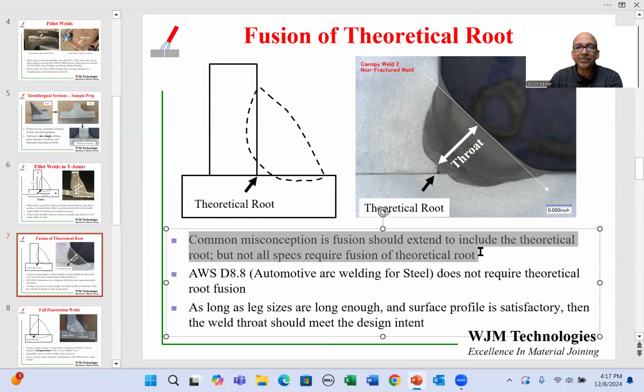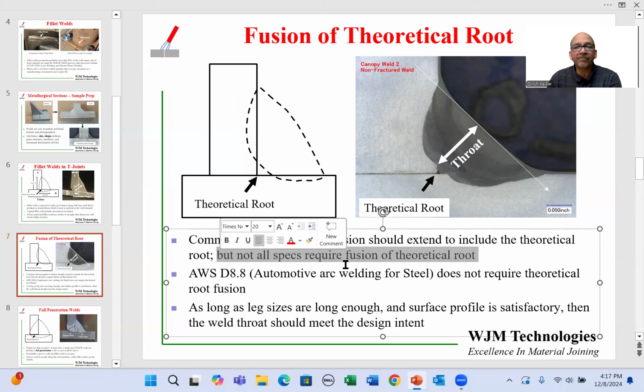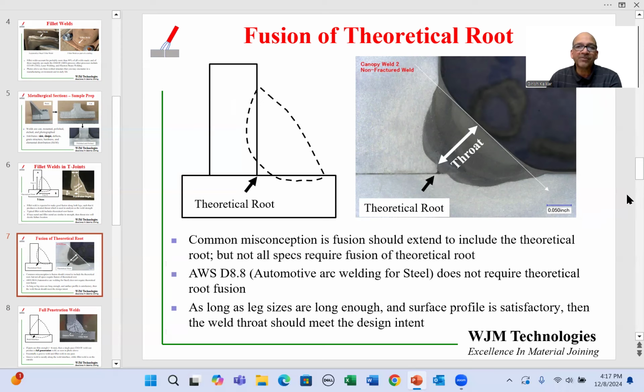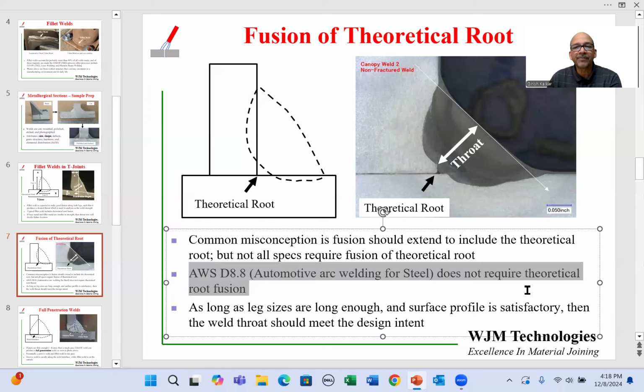Now, this is a common misconception in fusion welding, that it is a must to have theoretical root fusion. But what you'll find is not all specs require fusion at the theoretical root. The specs will often say that we need leg A of a certain size, leg B of a certain size, and an external profile of a certain shape, and that will effectively give you the correct amount of throat. But it is not necessary that the root is also fused. In fact, AWS D8.8, which is automotive arc welding for steels, does not explicitly require root fusion as long as the other metrics are met.